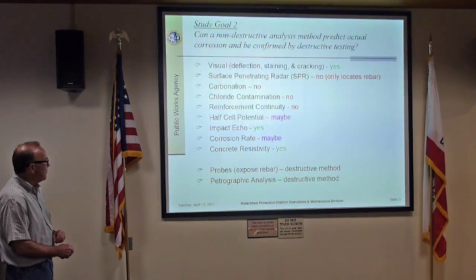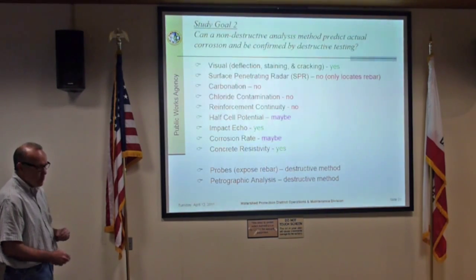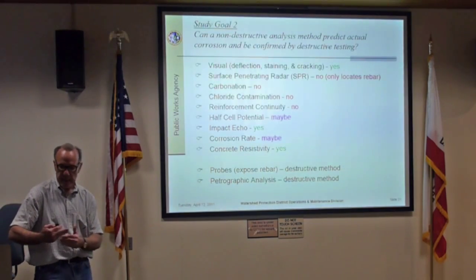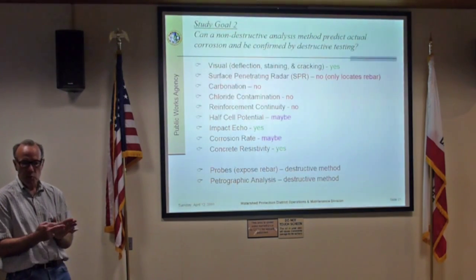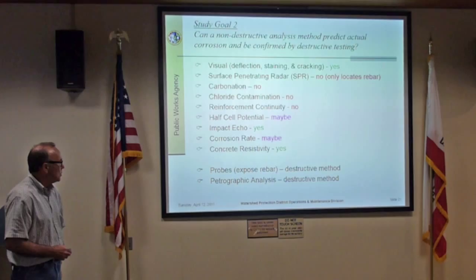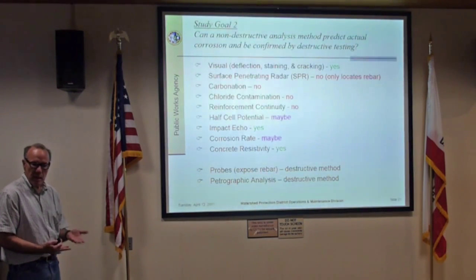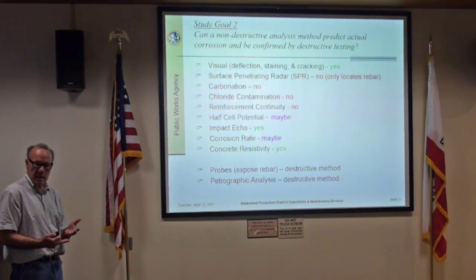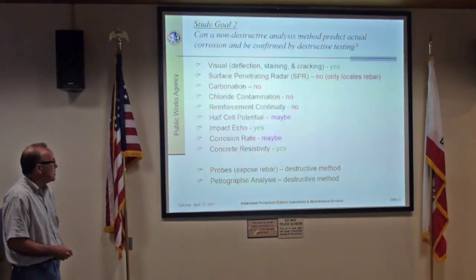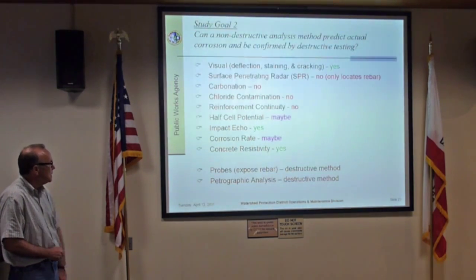Impact echo, we felt was a pretty good indicator wherever we were able to do that test next to the joint. We got a shift in those frequencies. It told us the concrete consolidation wasn't good. The voiding, where there was access to moisture and oxygen, was a pretty good indicator of corrosion. Corrosion rate was much like the half cell potential.